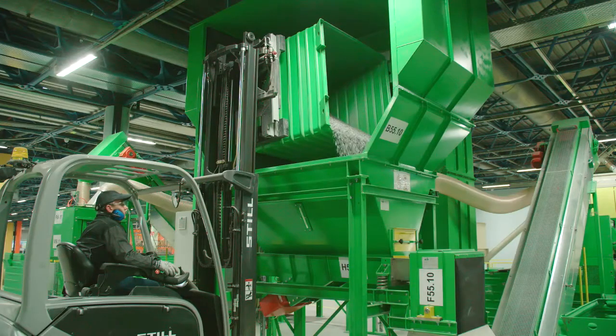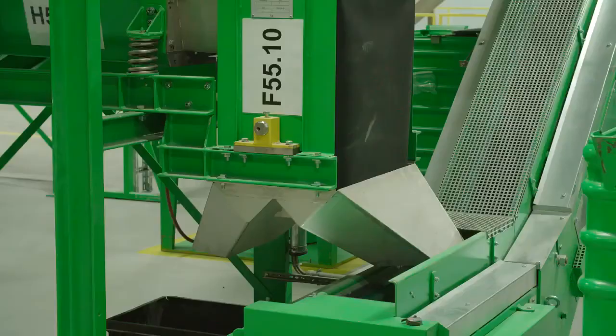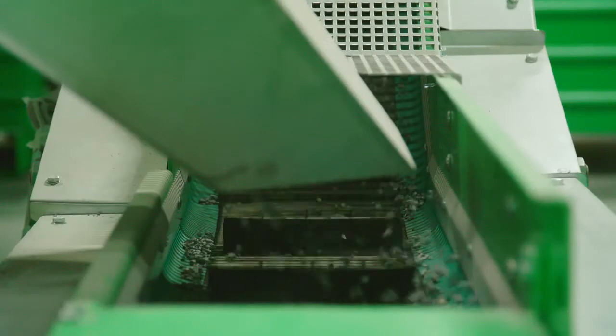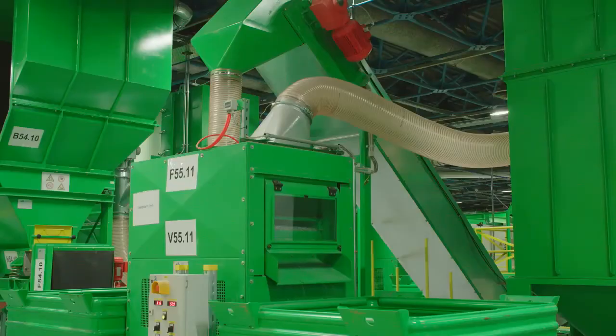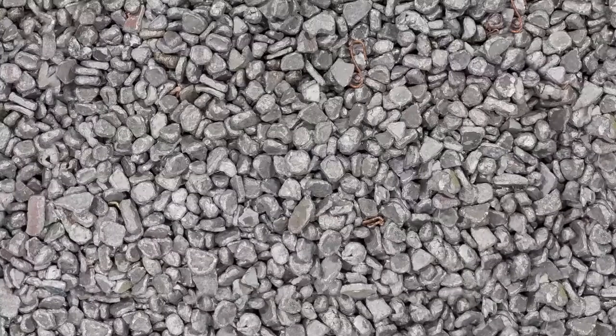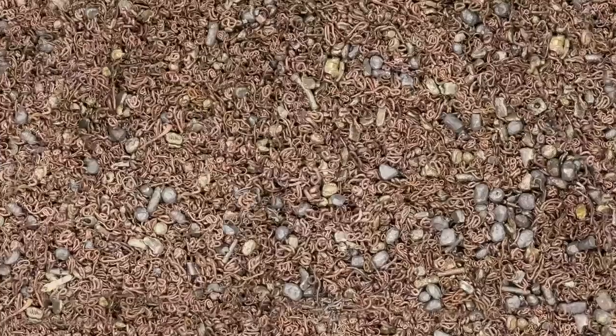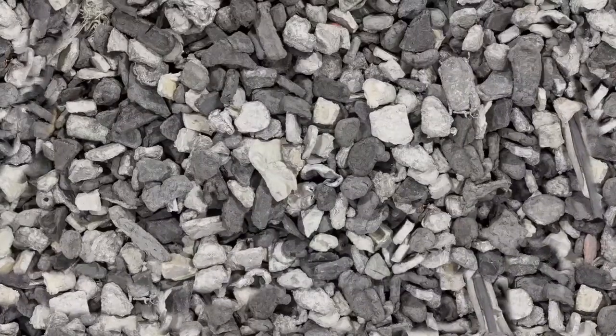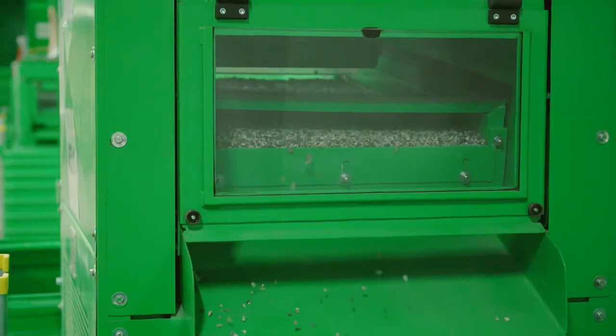The application of UMS air jigs to properly screened mixed materials separates metals from plastics as well as aluminum from copper and copper alloys. Having passed this process, materials show purities of more than 98% and often match the criteria for direct use in processing industries without undergoing a melting and conditioning process.